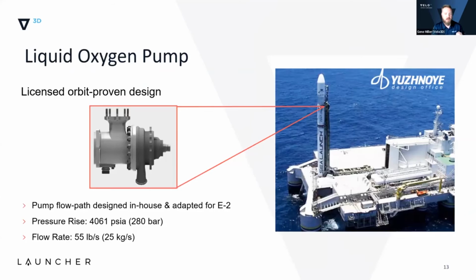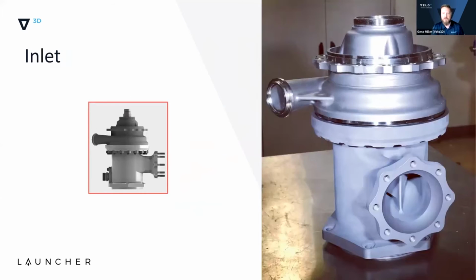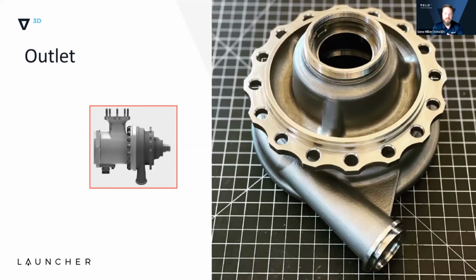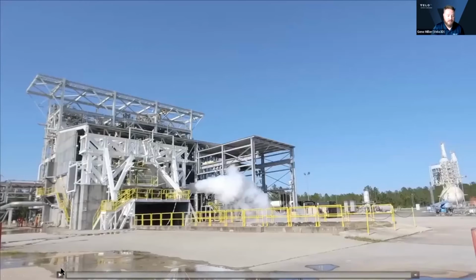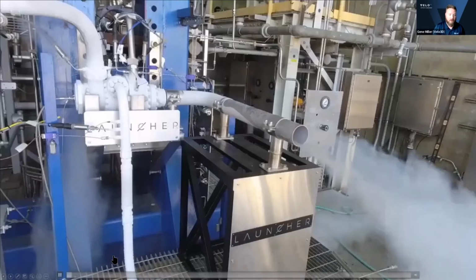Another example is a component for a liquid oxygen pump through Yuzhnoye and Launcher. We printed two components for this part, an aluminum housing as well as an Inconel outlet for the pump. This pump was assembled and tested. The inlet is the aluminum part on the bottom, and the outlet is the portion on the top. This was Inconel 718. And this was tested at cryogenic temperatures by Launcher and ran for 2 minutes. And this is a great example of a first article success. Right out of the gate, the pump ran beautifully for about 2 minutes.